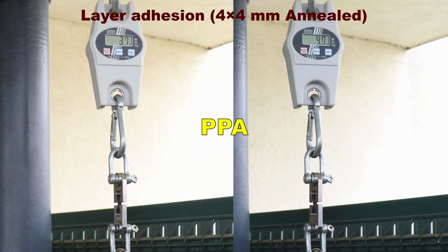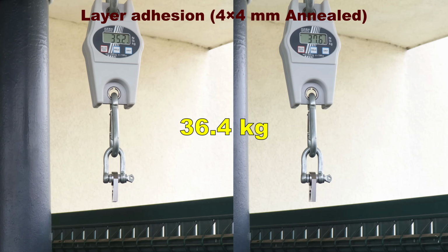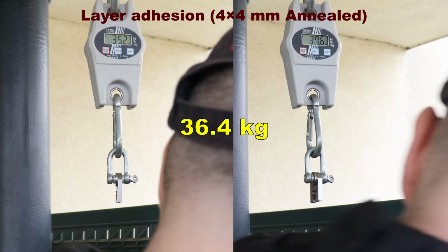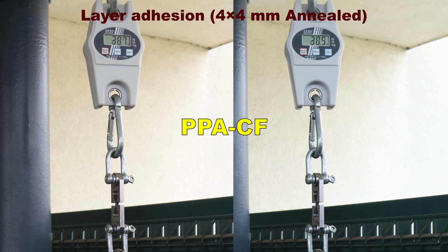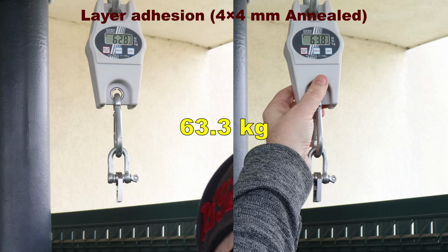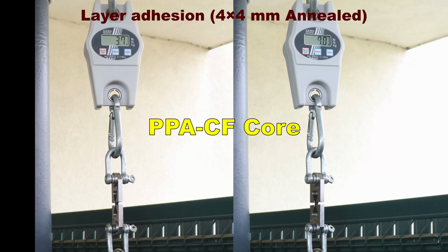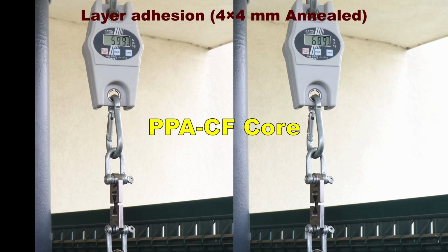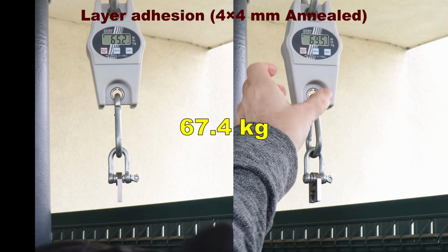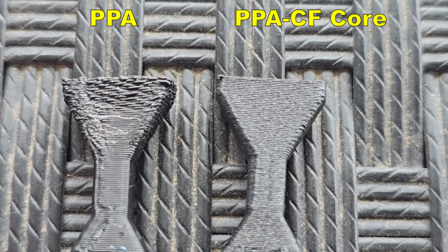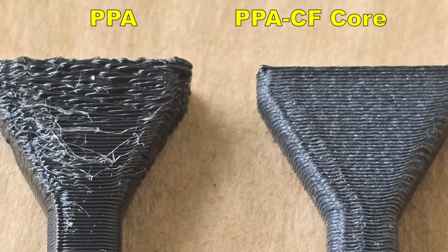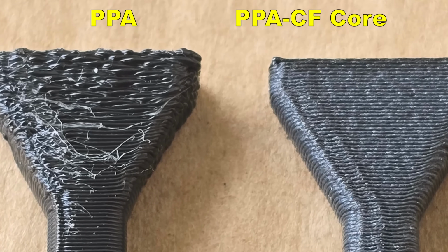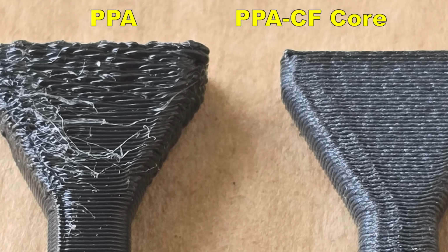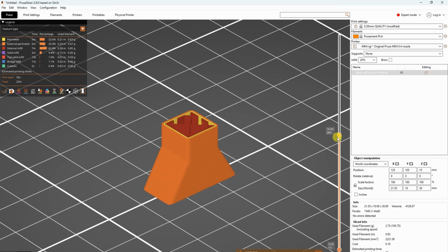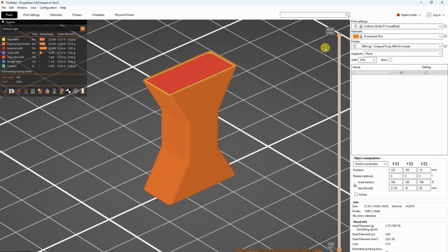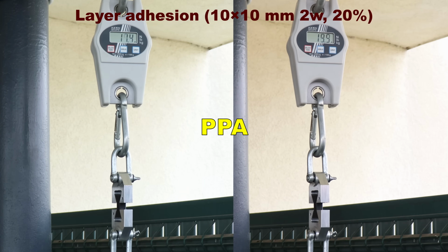And now the annealed version, PPA, carbon fiber version, again much stronger, and the core even stronger. Now question is, why is PPA weaker here? There may be two reasons. One is the lower print temperature, and the other is not enough part cooling and you don't have nice aligning shape. Another layer adhesion test, a 10 by 10 mm smallest cross section area with 2 walls and 20% infill.